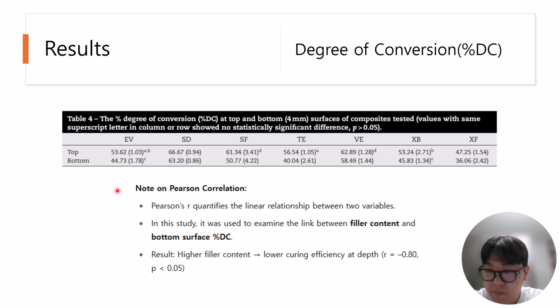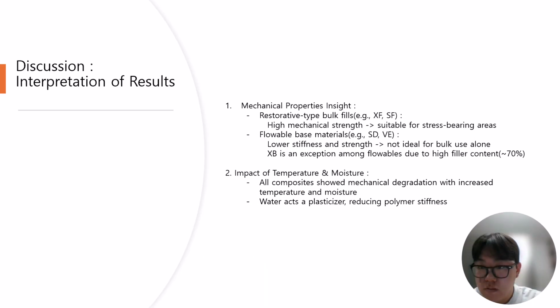Now, let's talk about the Pearson correlations. At the top surface, there was no significant correlation between filler content and degree of conversion. But at the bottom, there was a significant negative correlation, r equals minus 0.80. This means that materials with more filler cured less at the bottom because the light couldn't penetrate as well.